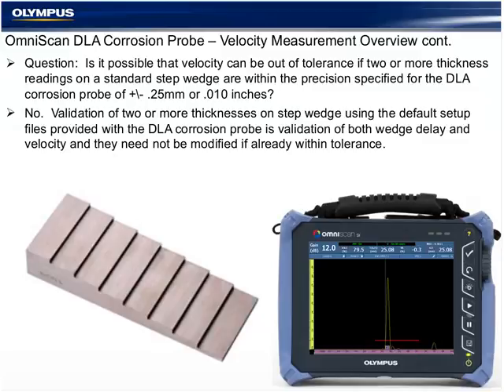Velocity and wedge delay. So is it possible that the velocity can be out of tolerance if 2 or more thickness readings on a standard step wedge are within the precision specified of 0.25 millimeters or 10 thousandths?